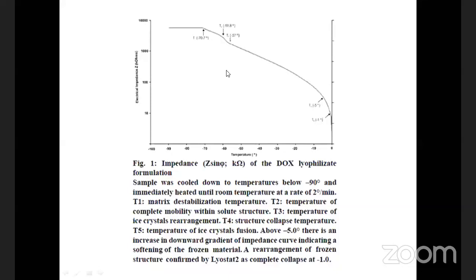That is again because we have to compare Lyostat with FDM, and a combination of these two will give us correct collapse temperatures. T3 represents the temperature of ice crystal rearrangement. Again, there is a minor inflection. Whereas T4, the structure collapse temperature, this one, because there is a sharp change in the direction of the curve. So this represents the complete collapse of the structure of the material that we are trying. Whereas at T5, temperature of ice crystal fusion, at this particular temperature, the complete mass is fused and it becomes a liquid. So it is again confirmed by the Lyostat as a complete collapse at -1 degree Celsius.